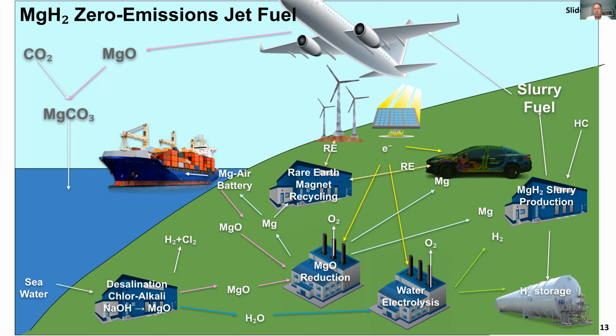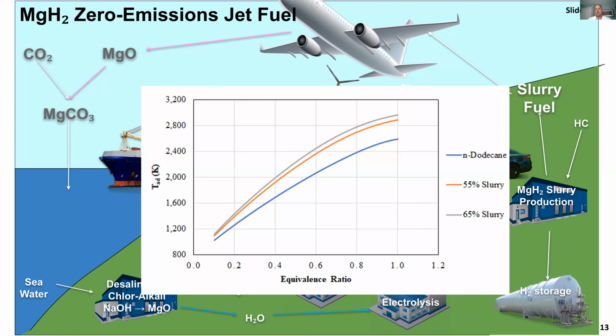Using an open source combustion thermodynamics program called Cantera from the MIT Laboratory for Aviation and the Environment, we've calculated the adiabatic flame temperature versus ratio of fuel to stoichiometry with air. An equivalence ratio of 1 corresponds to a stoichiometric combination of carbon or magnesium plus oxygen to CO2 and MgO, and carbon or magnesium hydride with the hydrogen forming water.